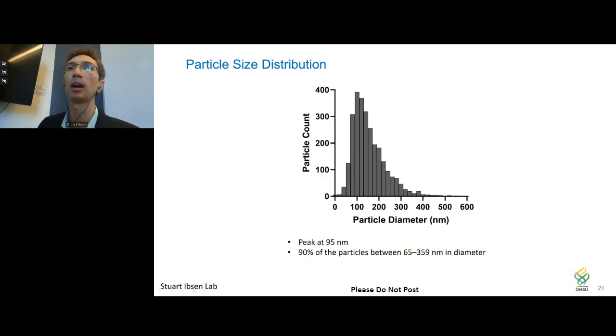Now, we've been able to characterize the nanoparticles that were collected. We can recover them off the chip using various techniques. And we find that the peak of the size distribution is 95 nanometers, with 90% of the particles being from 65 to 359 nanometers. And we can adjust this size distribution based on the frequency that we apply to the chip. So by changing the frequency that's applied of the electric field, we can change where the peak of that size distribution is located. But for us to be able to go for exosomes and other extracellular vesicles, this 95 nanometer peak is really ideal. So we've been able to tune this really well to be able to go after the particles that we're interested in.